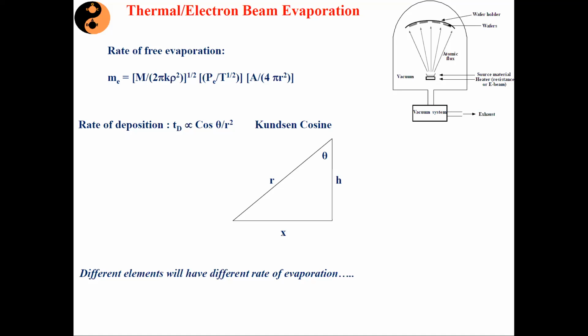If I have to grow a material like iron or copper or titanium or cobalt or silicon, all these different materials can be easily grown by thermal evaporation or electron beam evaporation. But suppose your compound has some composition like zirconium titanate or barium titanate or lanthanum manganese oxide or BiFeO3 or yttrium barium cuprate. That means you have more than one element present in its composition. And all these elements have different Z numbers and hence different molecular masses. Since they have different molecular masses, their rates of free evaporation will be different.